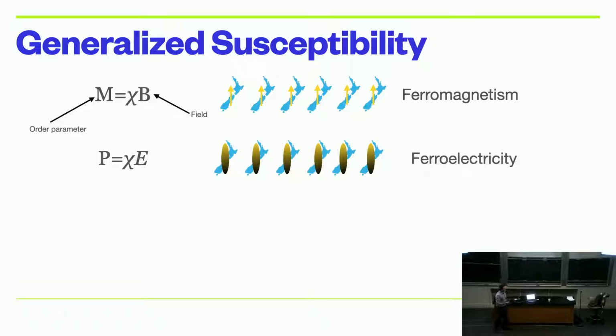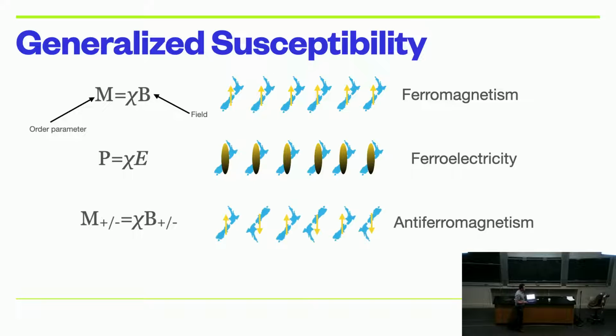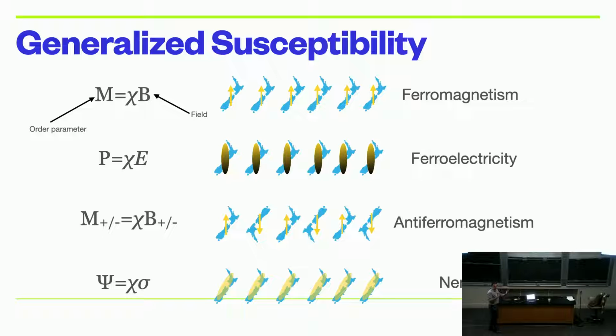If it's a ferroelectric, then it's the electric polarization and then a ferroelectric susceptibility. If it's an antiferromagnet, then it's what's sometimes called the staggered magnetization. That's the order parameter, and I don't know what this number is anymore. If it's a nematic transition, which is a kind of anisotropy in the system itself, then the anisotropy of the system itself will be proportional to what's sometimes called the nematic susceptibility, and the field there could be like a strain, or could be an electric field, or anything that couples to the anisotropy of the system.